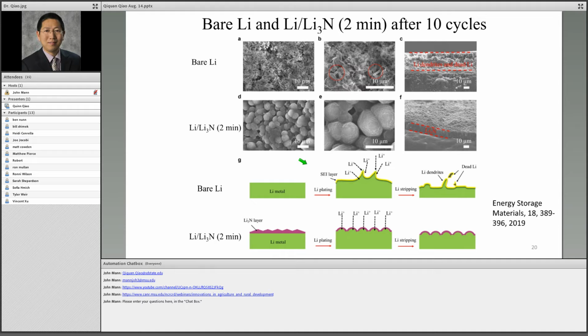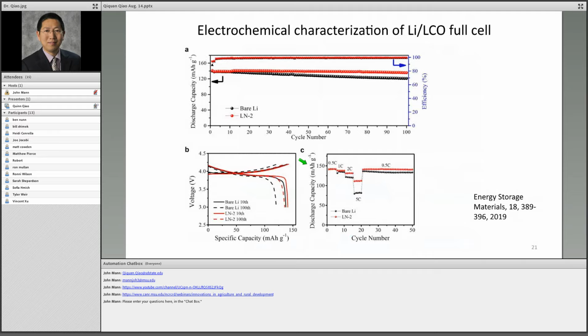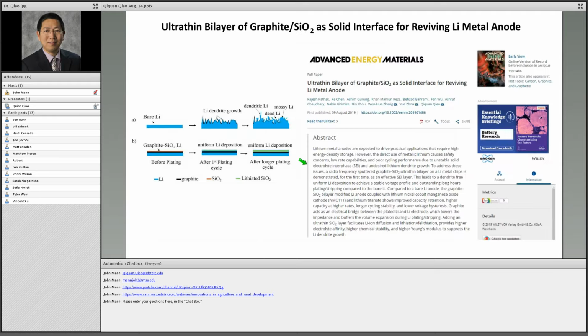And then here from the SEM, you can clearly see there is some lithium dendrite growth. Once you have this lithium nitride, you see there are no needles here. The needles cause problems. And the same thing in the cross sections: the lithium nitride shows very compact layers. Next, if you look at the capacity and performance of the batteries, you can see the battery works very well with lithium nitride, with 100 cycles as I show here. The capacity has been improved using lithium nitride, especially after certain cycles, like 10 or 100 cycles. So you can see the lithium metal batteries have been improved.